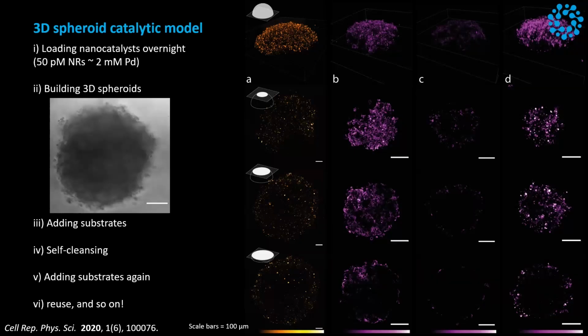You produce the pink fluorescent. Then you let it rest for 1 day, and it is self-cleaned at this point, and then you do it again. So even in a model like that, you can imagine that you could have even a kind of tissue-like model in your skin, and with this palladium reactor, you get injected so that you only produce the drug where you have the palladium. Okay, it's not something that I want to have palladium inside my skin, but it works very nicely.